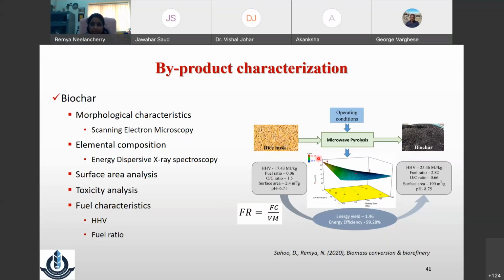Now, when the microwave pyrolysis process was optimized, in the optimized condition, we could get a pyrolysis product, that is biochar, which is a highly carbonized fuel, with the higher heating value on par with coal. Indian coal has almost the same heating value, 25 to 30 megajoule per kilogram. So it was a good biochar with high heating value, improved fuel ratio, and oxygen to carbon ratio was significantly reduced.